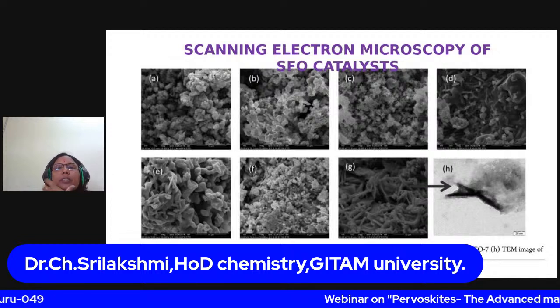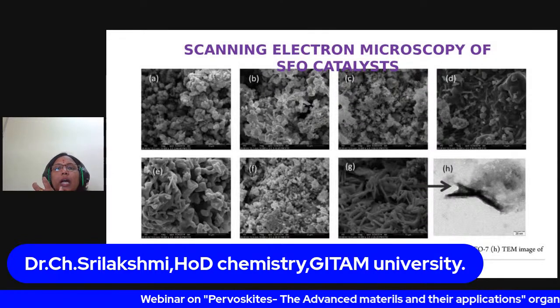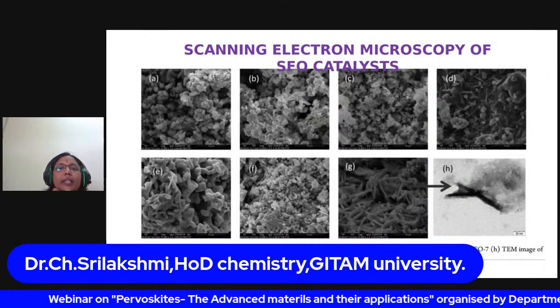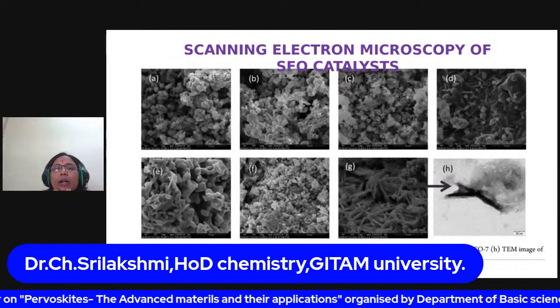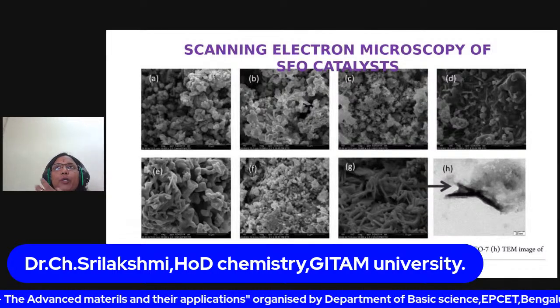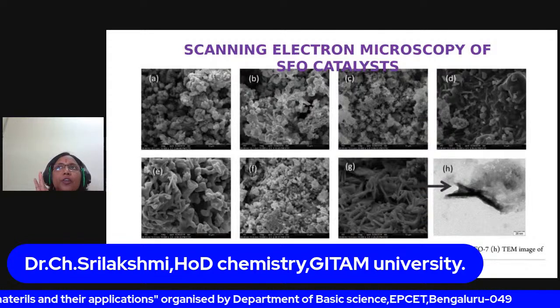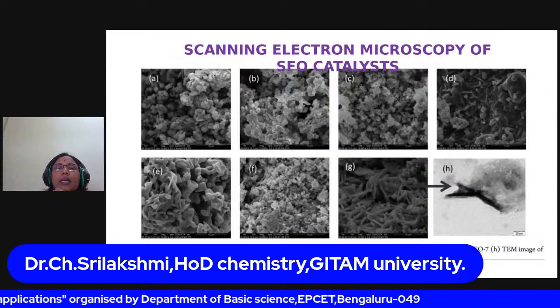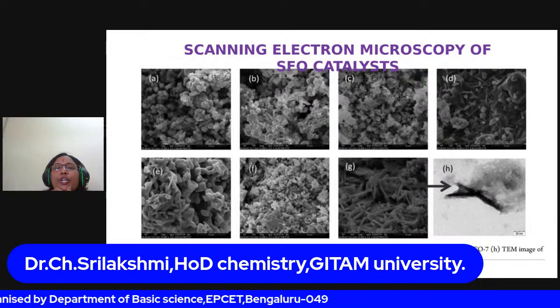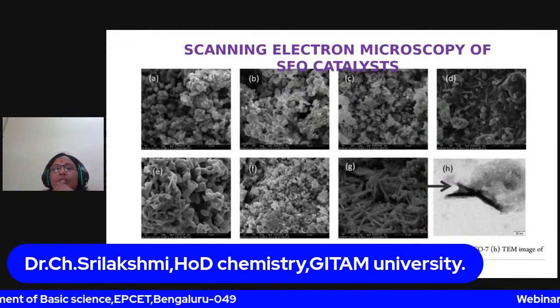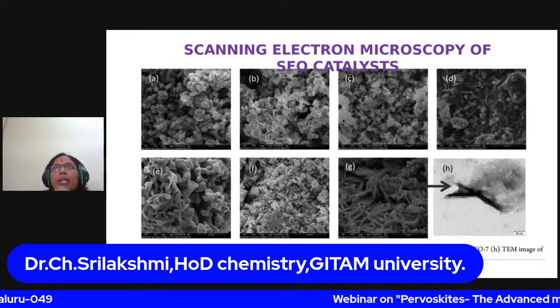Because of this magnetic nature, this compound shows highly dense agglomerated spherical particles. But at last, for the sample prepared using a combination of all three fuels, the morphology is changed to a plate-like structure, a star plate like this. This was further confirmed by TEM analysis.